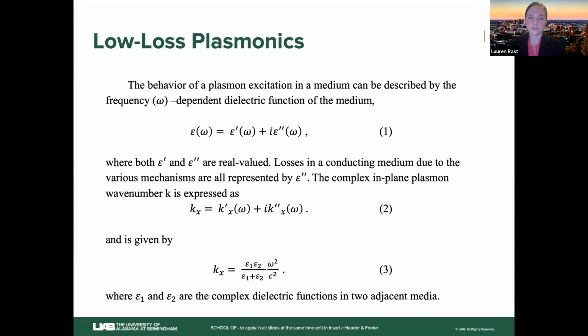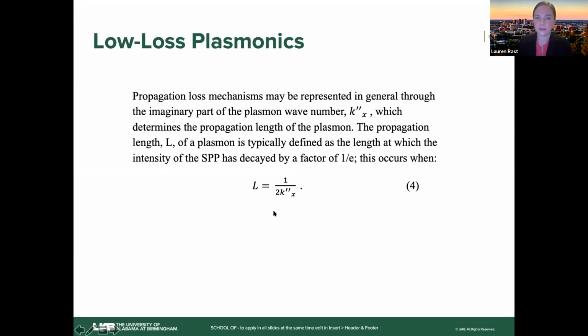And so we have a real and imaginary part of this dielectric function, and losses in a conducting medium due to various mechanisms that we already mentioned are represented by epsilon double prime. The complex in-plane plasmon wave number is given on the page, and we're just going to use that to define this quantity, which is the propagation length of a plasmon. This is typically defined as the length at which the intensity of the surface plasmon polariton has decayed by a factor of 1/e. Okay, so we can define this quantity, and then we can say some very specific things about which types of materials have longer propagation lengths. And then we'll look at this quality factor as well in just a minute.